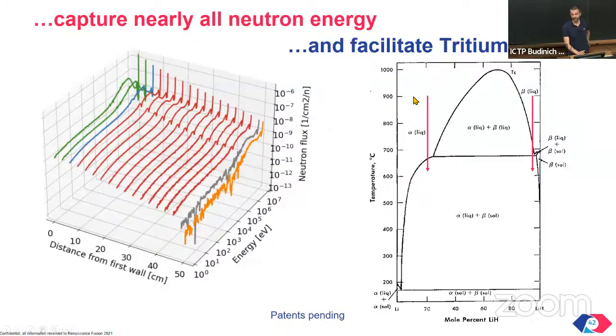There is an additional advantage. This solution of lithium hydride also allows us to extract the tritium. So shown on the right is the phase diagram of a solution of lithium hydride, concentration on the axis, temperature on the other, and various phases. And lithium hydride, deuteride, and tritide are chemically very similar to each other. So this is in fact a concentration of hydrides, plural.